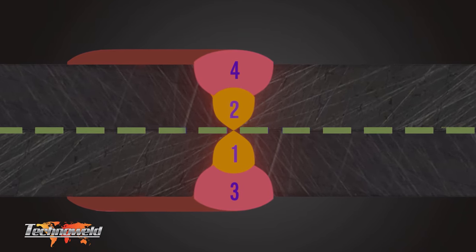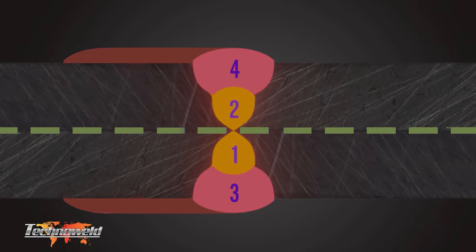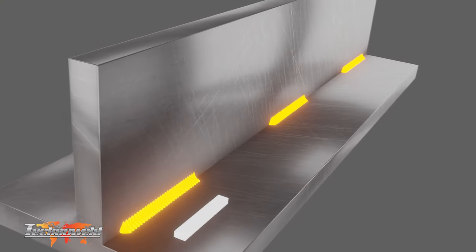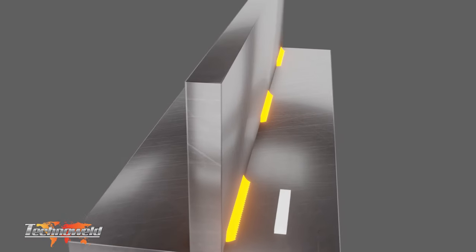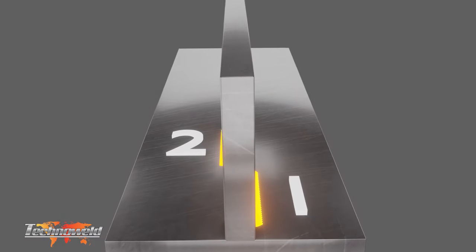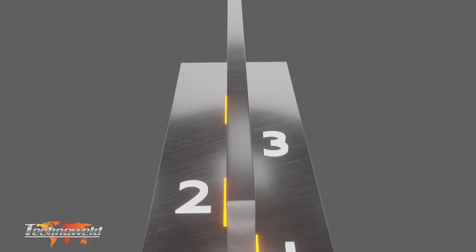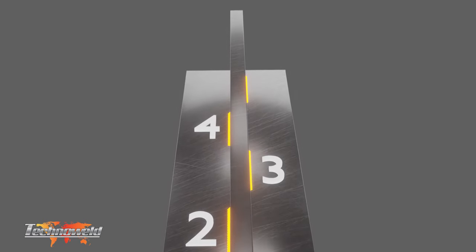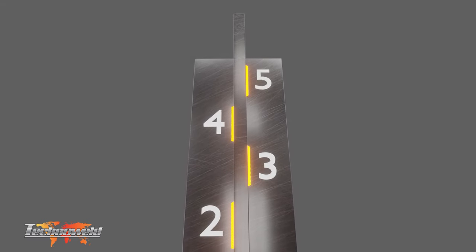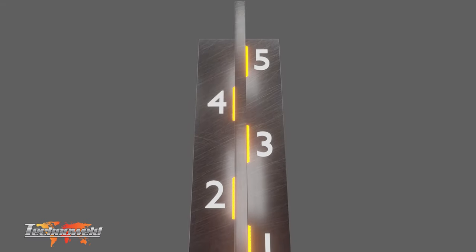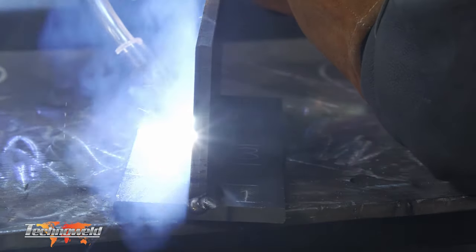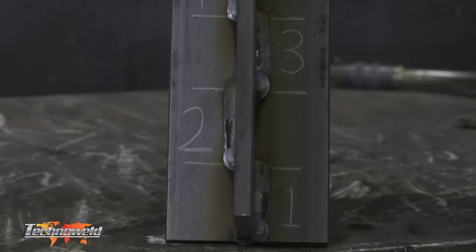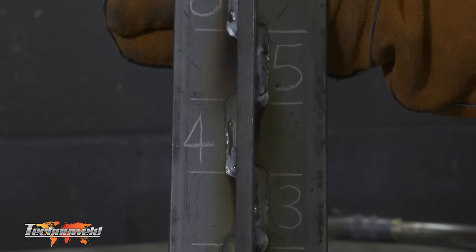Intermittent welding as discussed in rule one can also be used on jobs like this t-fillet weld. By alternating the weld from one side to the other, we are creating opposing forces that will both counteract each other. By welding about the neutral axis, these forces' effect will be minimized and will therefore keep the job relatively straight, ensuring distortion is kept at a minimum. Moving along the weld joint from one on the right hand side to two on the left, until all five marked welds are complete, the result is a straighter weldment with minimal distortion.